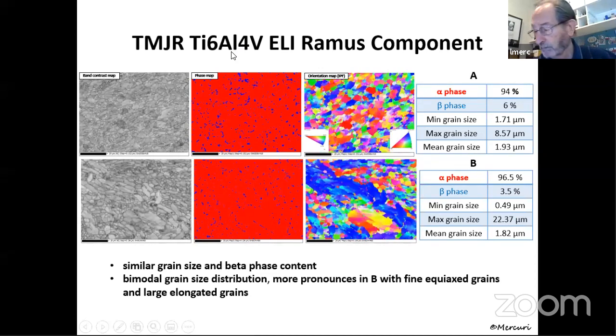So look at titanium. We use electron backscatter diffraction because this is the scanning electron microscopic picture of specimen A from 1 company, specimen B from another company. Now, titanium comes in 2 phases, depending on how it's melted. There's an alpha phase and a beta phase. The alpha phase is the strong phase, and that's represented by the color red. The beta phase is the softer phase, and that gives titanium its ductility. So you want a lot of alpha phase and very small beta phase. So what you see here in specimen A and specimen B, that the red, which represents the hard phase, and the blue, which represents the soft phase, are pretty similar, okay?